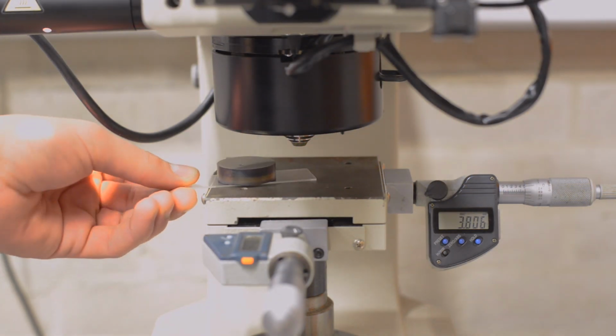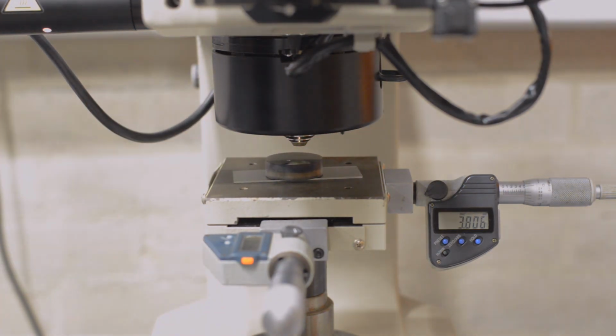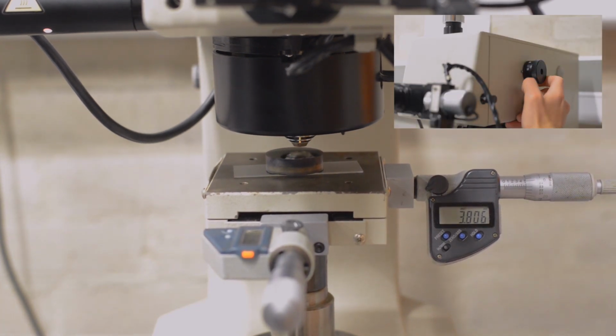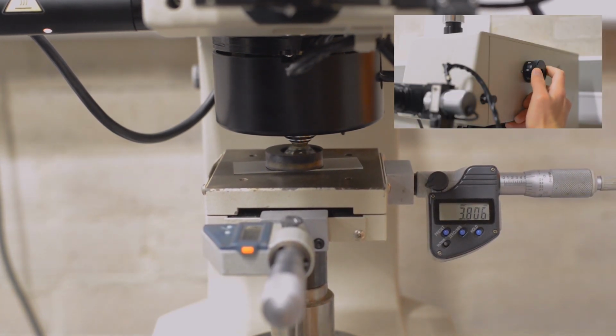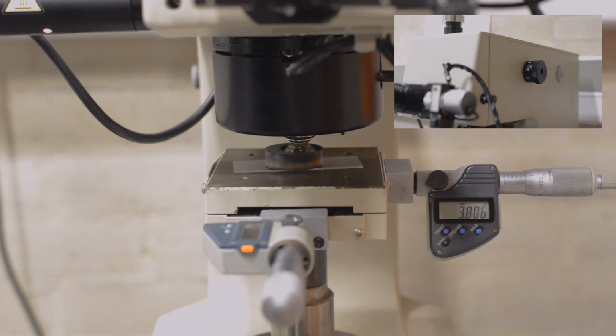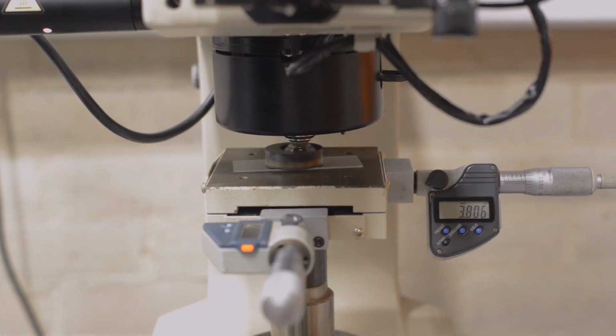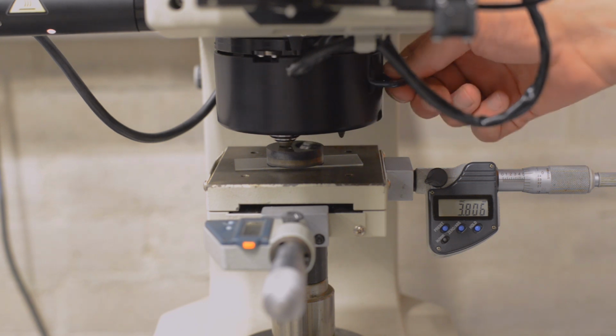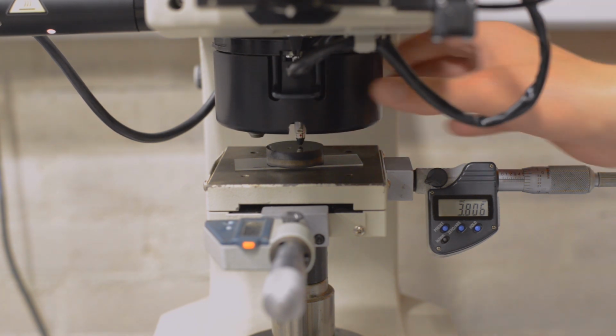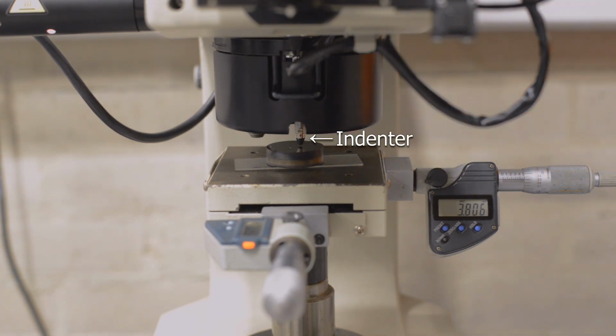The first step in testing your sample is of course loading it onto the machine. Whilst you are doing this, it is important to think about what load you wish to apply to the sample, as although a larger load will provide you with a larger indent, making for easier and therefore more accurate measuring, the resultant indent is influenced by a stress field zone of approximately 10 times the indent depth. So if you are measuring the hardness of a surface layer, the underlying bulk material is more likely to influence your result.